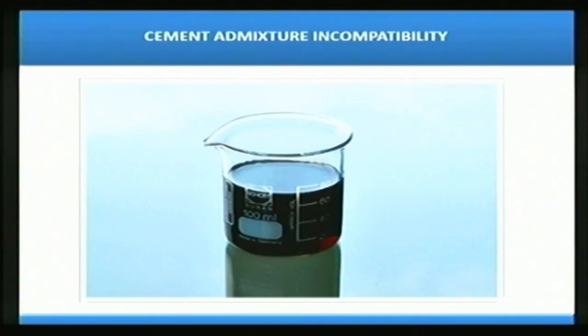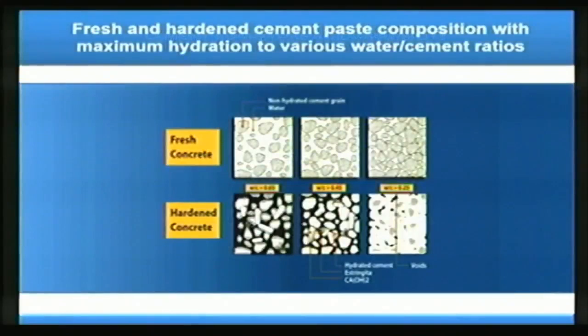So the requirements we have been associated with are also too stringent. You need a concrete with strength, high workability, and longer slump retention. Sometimes we have also seen that the concrete is kept for 3 hours or 4 hours, things like that. And maintaining that consistency in quality of concrete becomes a challenge, of course, at various water cement ratios ranging from 0.65 to 0.25 and 0.2.